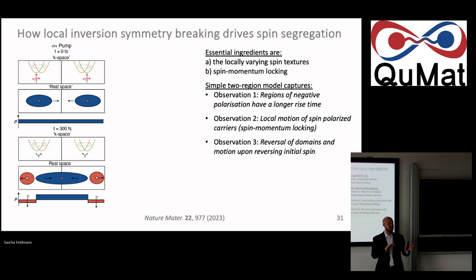Let's for now be agnostic about the origin of this inversion symmetry breaking, but let's say it's there. And what I then say is we just define two neighboring grains here with locally different direction in which the inversion symmetry of the crystal structure is broken. So let's say the one grain is strained in this way, this octahedral tilt here, or this little deformation, and in the other neighboring grain, it's in that way, and they have therefore different spin textures also locally. Sketch kind of here. Now, what will happen if I just flood the whole system with a circularly polarized, say, right-handed spin-up population at time 0 is, of course, you will also get this polarization response. So initially all blue shown here in this positive polarization.